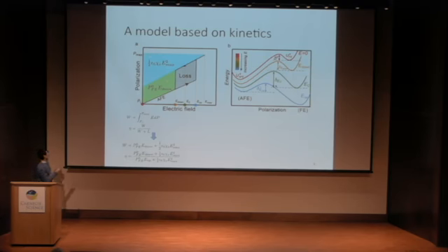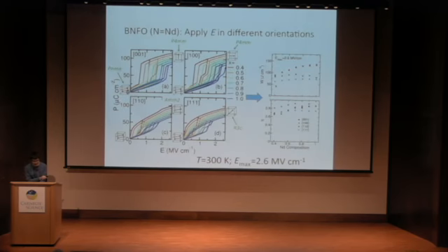It's 1/2 of the dielectric constant times the E max squared. Some of the results can be explained by this expression. Let me go back a few slides here. For example, the 001 field has a larger energy density than the 111 field because it has a larger polarization, and also the E down is larger than that.